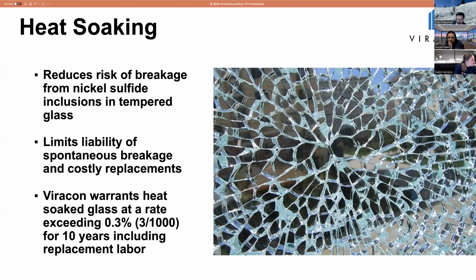How do we prevent it from happening? We heat soak the glass. We basically cut the glass, temper it, put it into a heat soak oven for a specific amount of time at a specific temperature. If there's a nickel sulfide inclusion anywhere in that thickness, it's going to have grown enough, through the calculations of how long to be in there, that it would pop the glass. If it pops in the heat soak oven, we remove that glass and we start over. Those that didn't pop, we continue with fabrication.